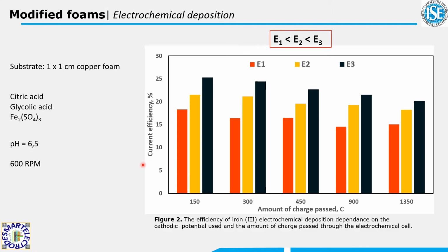Current efficiency calculations have been made using gravimetric data and can be seen in Figure 2. The deposition was performed using a magnetic stirring bar rotating at 600 rotations per minute. The overall efficiency of the deposition, regardless of the potential applied, did not exceed 30%. The cause for this is probably the adsorption of organic matter on the working electrode, effectively blocking the surface of the electrode.